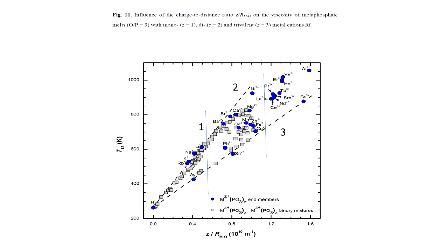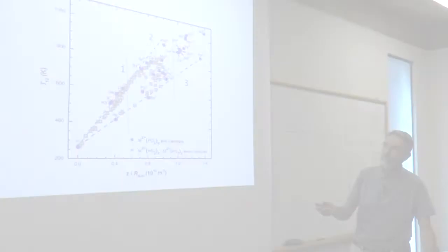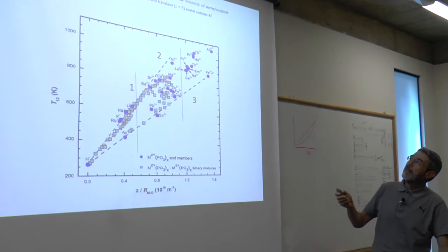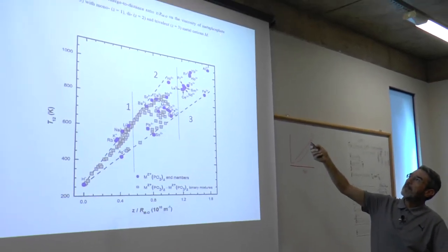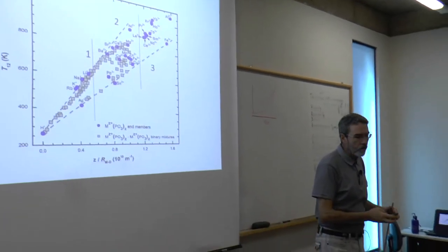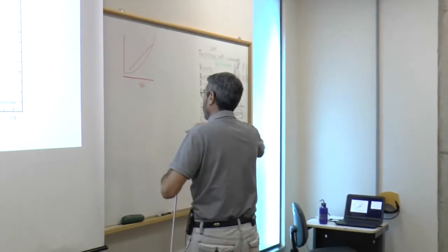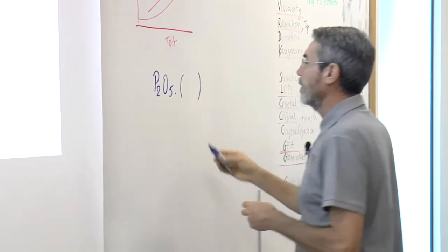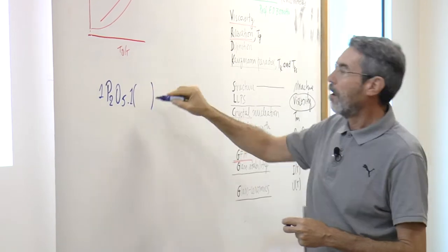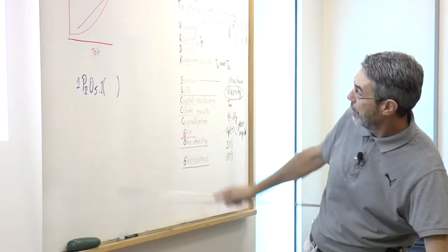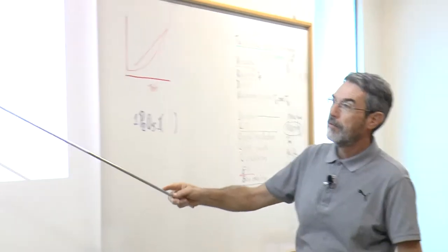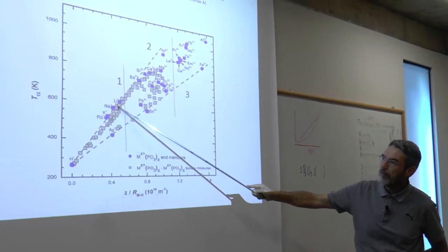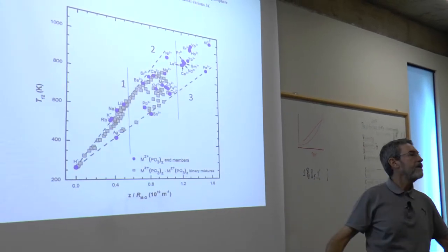So to summarize, this plot shows the effect of T12, which is always the TG here, for different oxides added in metaphosphate melts in this case. Metaphosphate is P2O5 dot some oxide. 1 mole of some oxide is added to this glass-forming P2O5. See, lithium, sodium, potassium, rubidium in the periodic table, decreasing the TG or decreasing the viscosity.